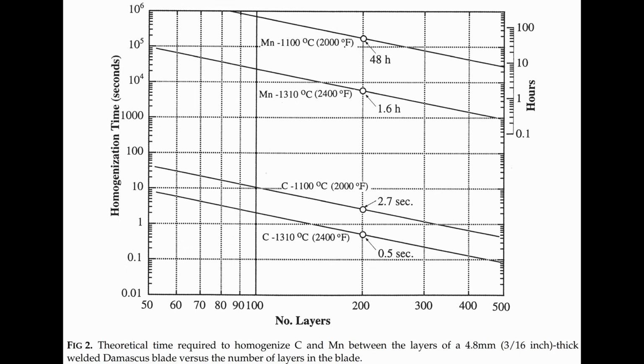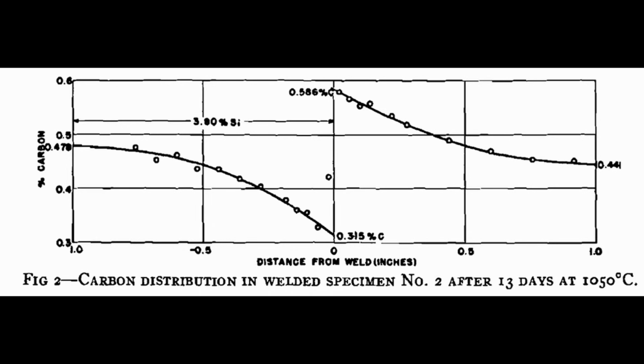But will carbon always completely homogenize, reach the same carbon content between the two layers? Not always, no. Even if the layer count is small. So there's a famous equation by a metallurgist named Darken, and he took a steel with high silicon and a steel with almost no silicon with about the same carbon content, 44 to 47 points of carbon. And when he held it for a long time at high temperature, he found that the carbon was diffusing into the low silicon steel and away from the high silicon steel.